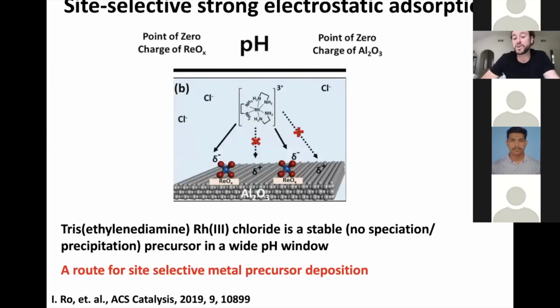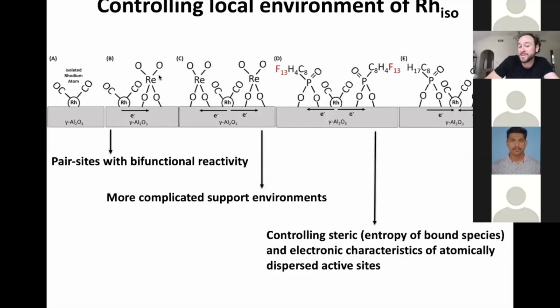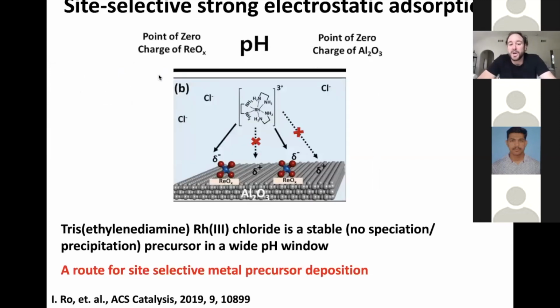I'll just show you how we're trying to get to the point where we're making these pairs of sites here. You can do what's called a site-selective deposition that we've tried to develop, where you can take a surface like alumina, and deposit down little bits of rhenia all over. Rhenia has a different point of 0 charge than the underlying alumina, and you can do the same with tungsten as well. And then you can use charged precursors, and you can try to use an electrostatic interaction between the charged precursor with cationic, and these little bits of domains on the surface, which are anionic and have a different point of 0 charge than the underlying alumina, to deposit these right as neighbors.